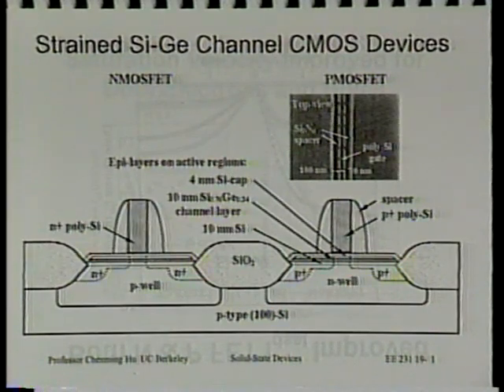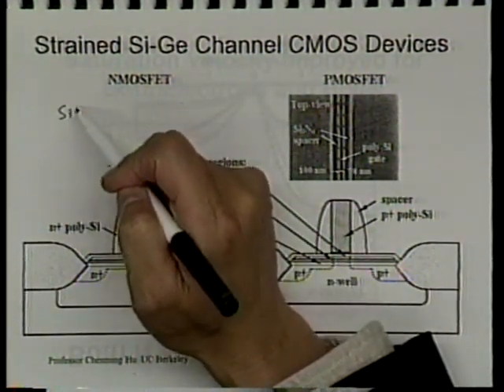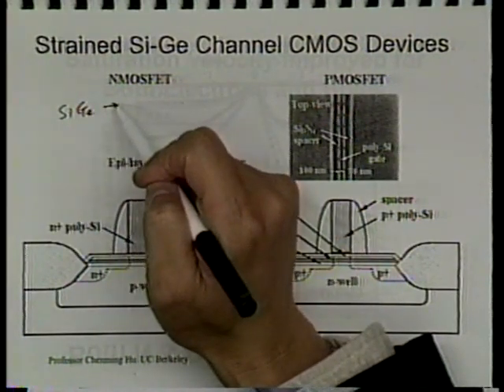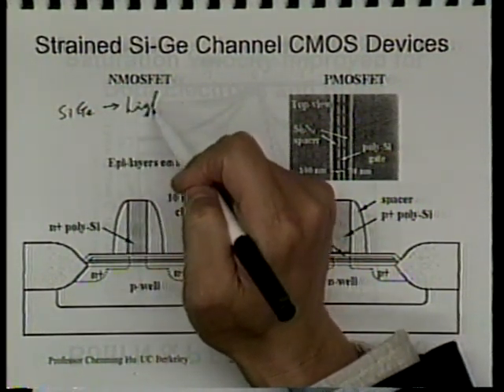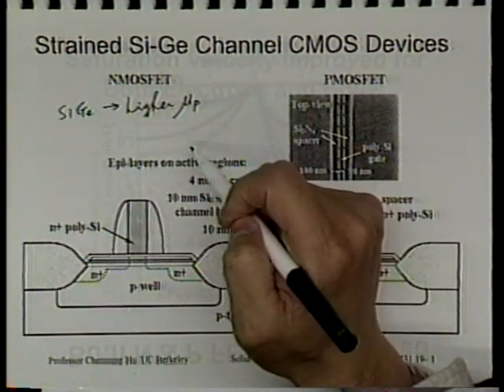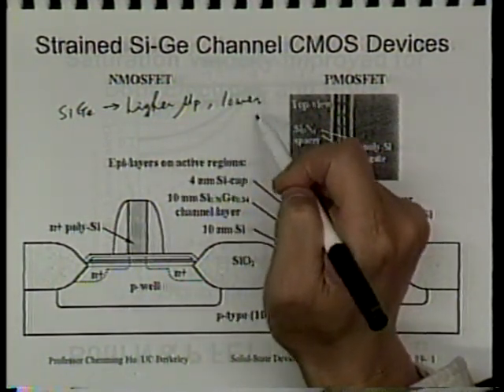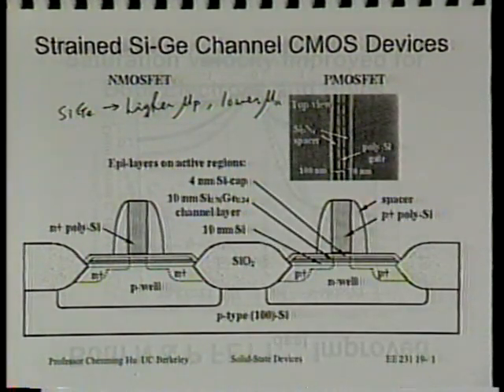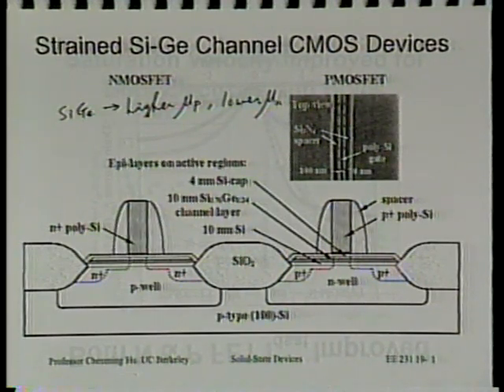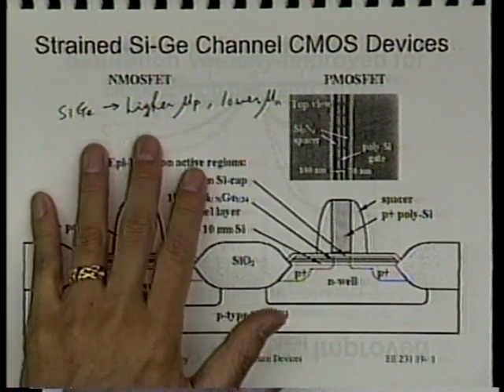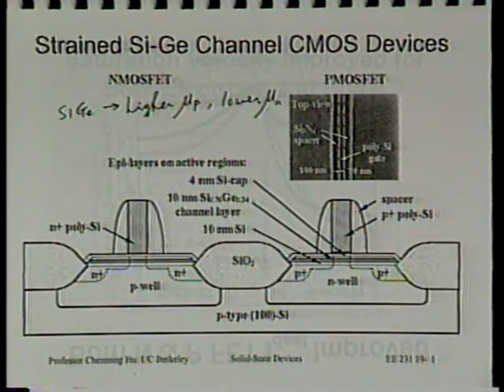So what's the whole point? Well, the point is, at least in the older way of doing things, it's known that silicon germanium has higher mu p, but unfortunately lower mu n. So for this reason, it really has not been taken seriously. A paper was written 10 years ago already that you can make CMOS in silicon germanium, but you end up with more current in the PMOS and less current in the NMOS. I don't like that. All right?